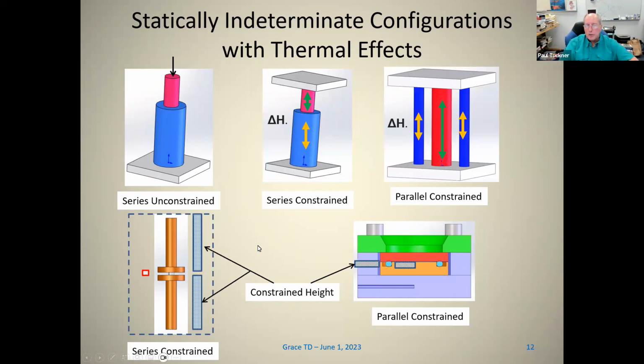Now what happens if you actually do continuous testing, you typically have a series constrained configuration. So the amount of compression that actually occurs here will depend on the length of the compressing surfaces, their stiffness, and their thermal expansion. In most applications for sealing, you really have a parallel configuration, which is what you see in a discrete setup. So you have to understand that if you're doing continuous versus discrete testing, you might not get the same values unless you have matched thermal expansions and distances to compare.